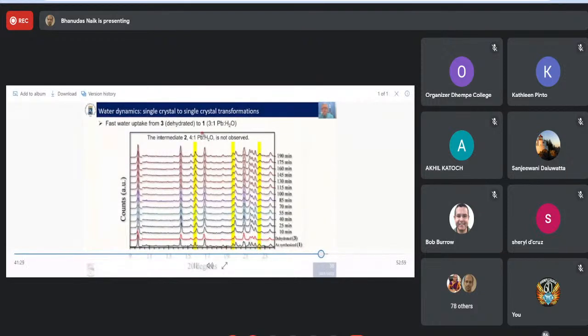And if you leave it in an environment with water, you can see over time, this peak goes back in again, this peak goes back in again, and this peak as well. You can see this one dislocates with the side, and it goes back in again. And after 190 minutes, a little over 3 hours, you basically have the same powder diffraction pattern as the original compound as synthesized. So this is reversible. So you can then dehydrate it, and it goes back again.